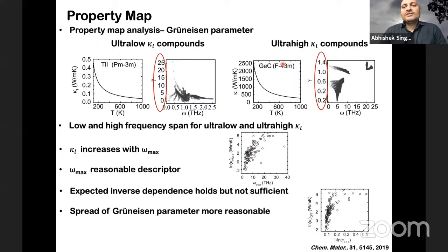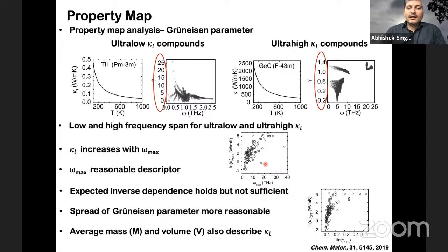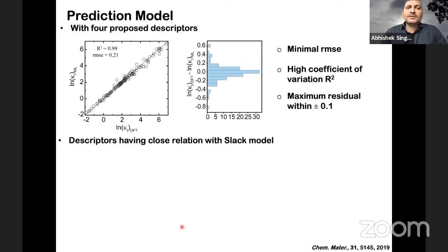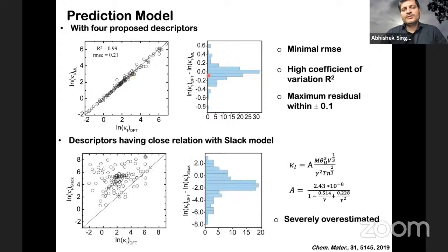But that was not sufficient because there were some more problems. So what we realized is that an integrated Gruneisen parameter up to 3 terahertz has the best correlation with kappa L. And mass and volume are the two other features which have a well-defined reason why they have a certain relationship with kappa L. So using these 4 parameters, we developed a model for the kappa L prediction, and look at that. It's one of the very beautiful models, very powerful, very low RMSE, very high R square, extremely low residual.